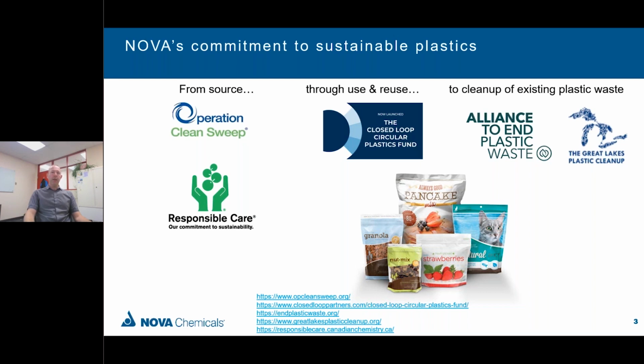Many flexible food packages are structures with 3 to upwards of 9 layers of materials. Often, some of the design functions are addressed with different materials in the layers. So for instance, there might be metallic foil or other polymers such as nylon. But packages that are made with mixed materials in the layers are not broadly recyclable. So by designing polyethylene products that have the appropriate properties, a package can be made of layers that are all variants of polyethylene, which is broadly compatible in recycling streams.